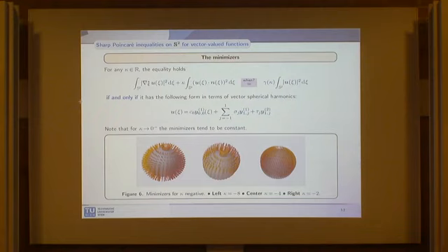The fact is that you could never hope that, even if kappa is really huge, the tangential configuration will play the same role as the normal one, due to the Hairy Ball theorem. So if you have a configuration from S2 to S2 and it's tangential, then you are no longer in H1. That's the point. So while for normal configurations you can expect that for kappa really negative you have this normal vector field as a global minimizer, you cannot expect a tangential vector field to play the same role for kappa really positive. So yes, but we are currently investigating the case kappa greater than 0.